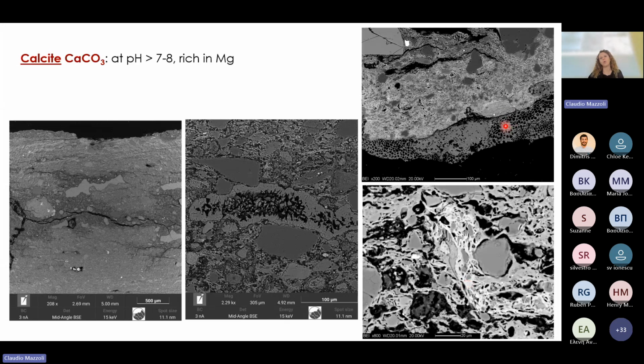And this happened, for instance, also here, in which this lighter part is affecting only part of the ceramic material, not reaching the core of the ceramic body. But let's say precipitating little by little from the outermost surface to the inner, but at a certain point stopping. Why is this happening? Because often a sort of barrier is created in which the fluid precipitates the secondary calcite, but then the fluids are not rich anymore in this ion, so they do not precipitate calcite in the inner part.